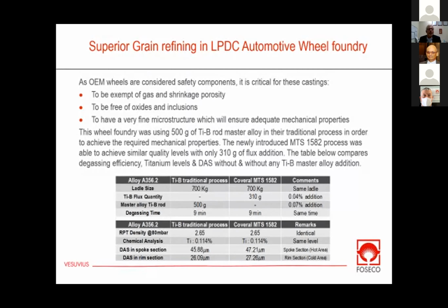We introduced our new process side by side with their traditional process. The ladle's the same. We completely removed the master alloy and added only 310 grams of our new titanium boron flux grain refiner, which comes out to 0.04% addition rate. We kept the degassing the same, so all other parameters are the same.